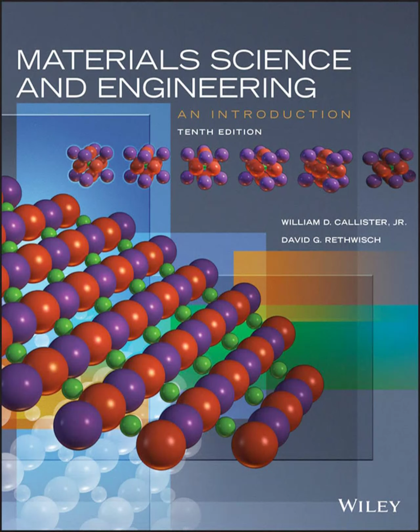Now, if you visualize the concentration profiles, drive-in looks different from pre-deposition. After pre-deposition, the concentration is highest right at the surface and drops off as you go deeper. But after drive-in, the total amount of impurity is fixed, no more coming in. So the peak concentration actually drops and moves inward away from the surface. The profile becomes broader and deeper. Okay, so it pushes the peak concentration below the surface.